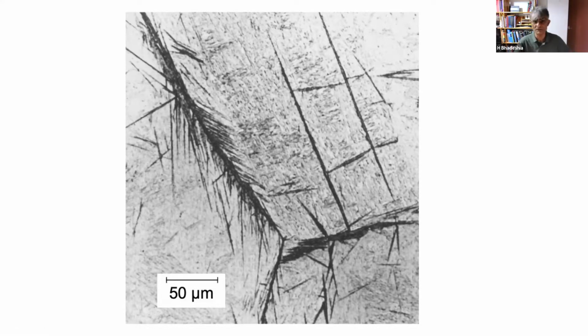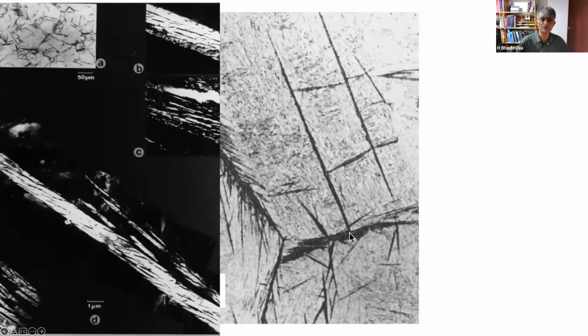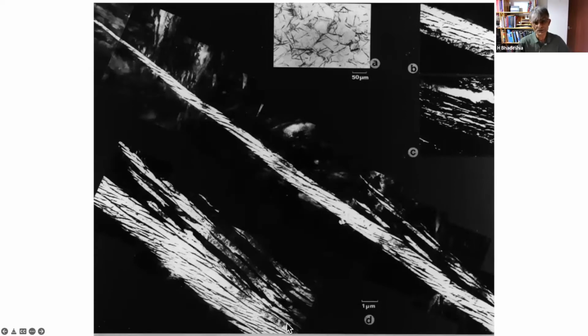But if I take one of these and I use transmission electron microscopy, then you'll see that this actually consists of thousands of small plates, like this, where you form a plate, it then stops, and you have to propagate by forming new plates, nucleating new plates. And the size of that small subunit is the same here as at the beginning. In other words, something is happening for these plates to grow rapidly, but they are stopped. And then you have to propagate this collection of plates by forming new plates, nucleating new plates.